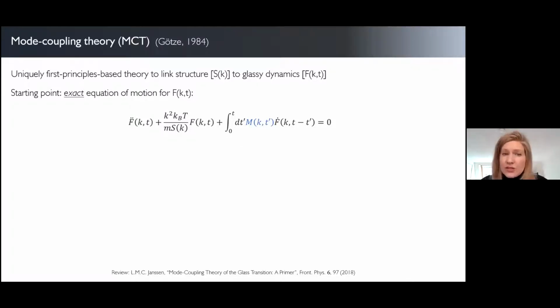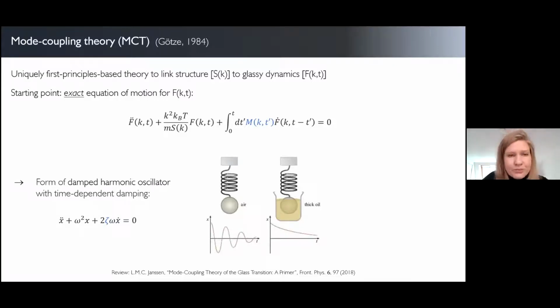Now, to give you an idea what this equation looks like, you can compare it with the form of a damped harmonic oscillator, which is really quite similar. There's a second derivative here, and there's a linear term here and here. And then finally, there's a first derivative here and here. So it's quite similar. But for a damped harmonic oscillator, the damping coefficient is a constant, while in our equation here, we have this function m that is now a time-dependent object. So this function m, you can think of it essentially as playing the role of a time-dependent damping in this equation. And you can also see that this function m has to be integrated over all previous times from time 0 up to the current time t. So this function is also called the memory function because it contains information about the past, the history of the system. Now, the key question is, what is this memory function exactly?